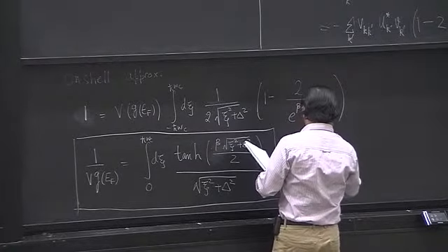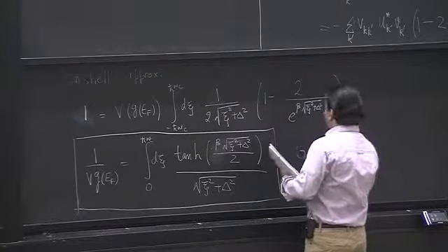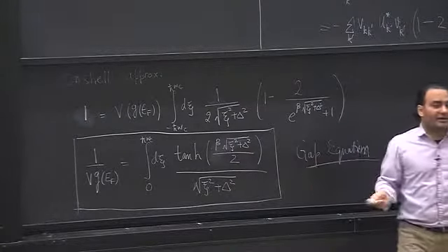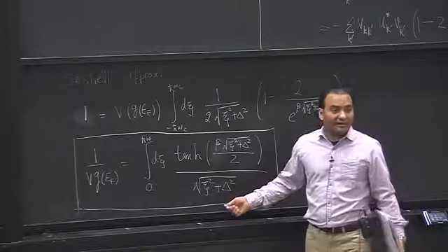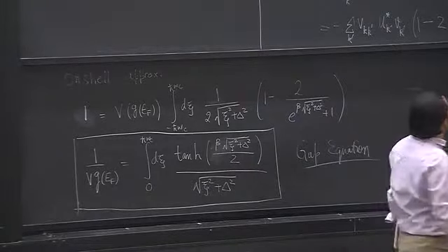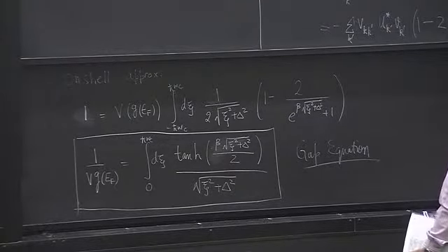So this is known as the gap equation. What that really means is this equation will give you the solution for delta, which we know is the gap in the spectrum from the definition of capital E k over there.